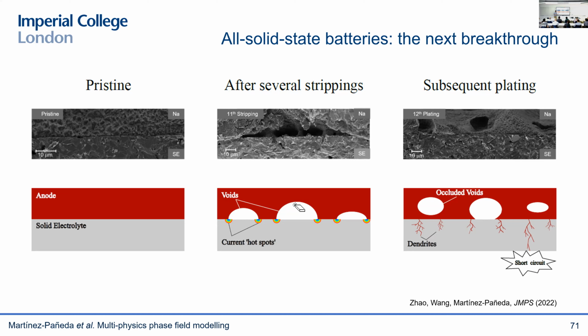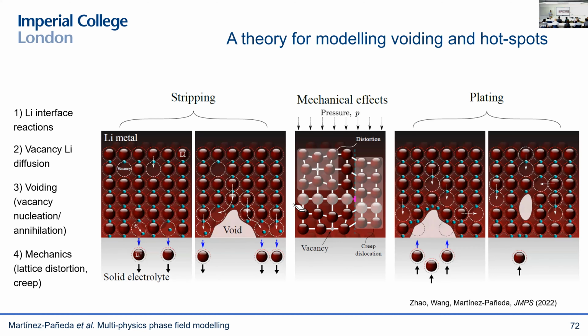So we need to understand what the current is at those edges, and we need to understand how those voids evolve. So again, a multiphysics problem that involves a moving interface. Not fracture anymore, but still a moving interface and a multiphysics problem. So we came up with a theory describing this physical phenomenon and a computational model. I won't get too much into the details, but these are, I think, the four main mechanisms. You need to capture the interface reaction, so the lithium atoms being detached during stripping or put back in during plating. You need to capture lithium diffusion, the back diffusion, so you have solid state diffusion within the lithium metal. So this is a transport problem. We use a transport equation for that.